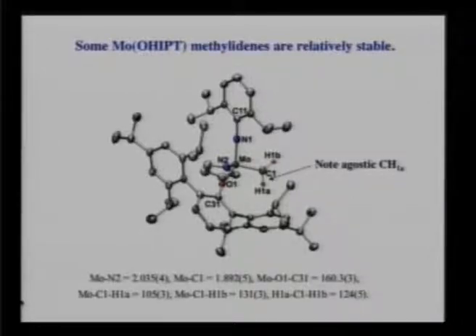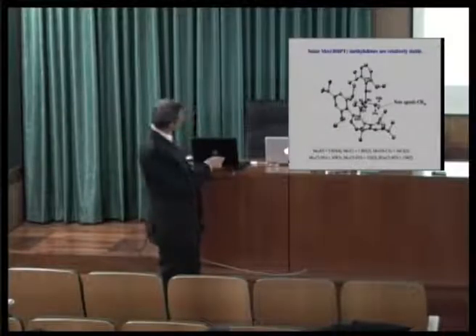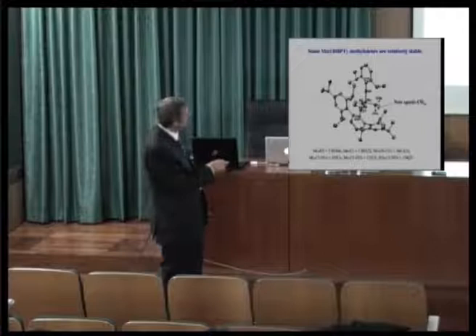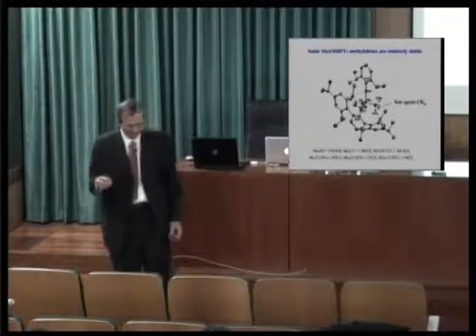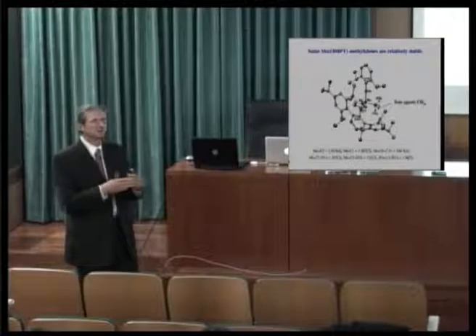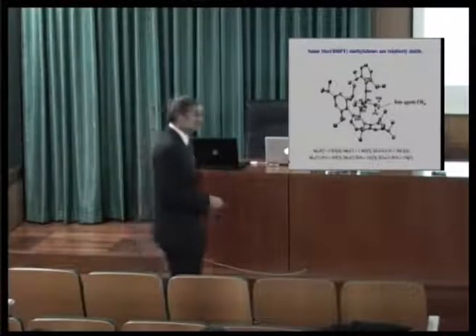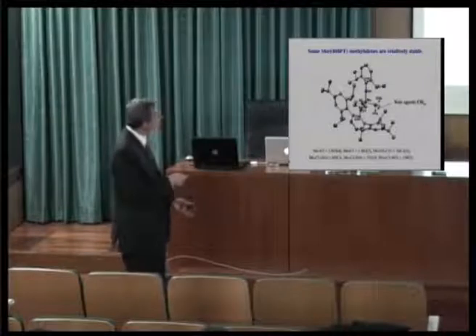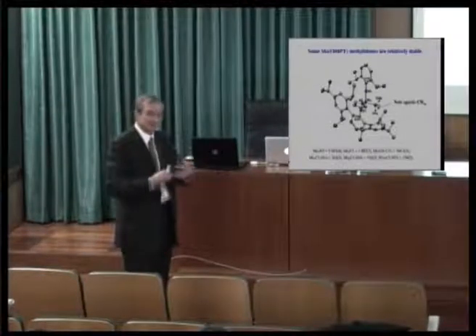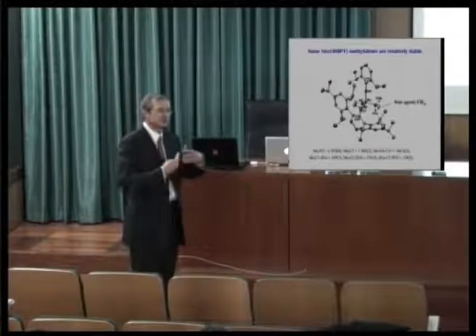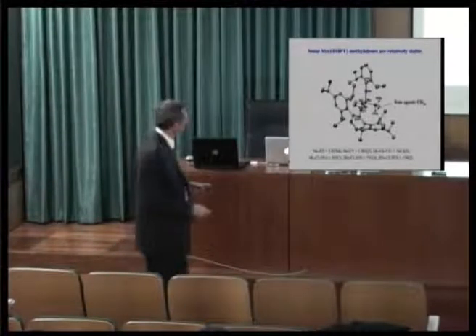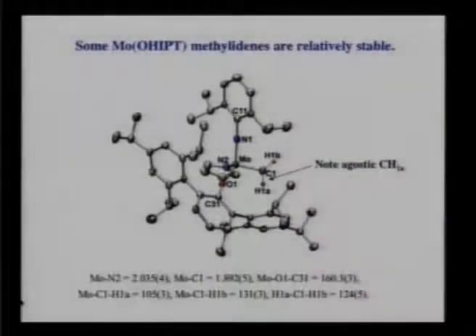efficient, besides the theoretical calculations that I told you about, is because the big ligand, like this HIPT ligand, makes even methylidenes, which are the most unstable alkylidene intermediates, they decompose bimolecularly very readily, stable enough to isolate, and therefore they are probably stable enough to last for a very long time in the reaction, and so you get many turnovers instead of rapid decomposition. So these large ligands are helping us to prolong the life of a catalyst in these metathesis reactions.